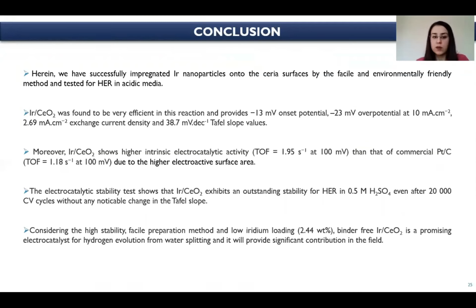The electrocatalytic stability test shows that iridium ceria exhibits an outstanding stability for the hydrogen evolution reaction in sulfuric acid even after 20,000 cycles without any noticeable change in the Tafel slope, onset, and overpotential values. Considering the high stability, facile preparation method, and low iridium loading, binder-free iridium ceria is a promising electrocatalyst for the hydrogen evolution reaction from water splitting.